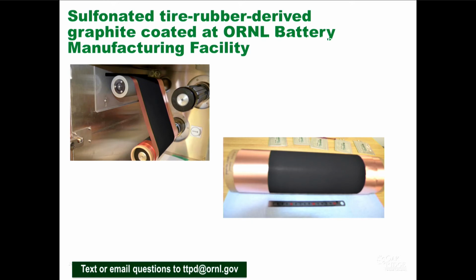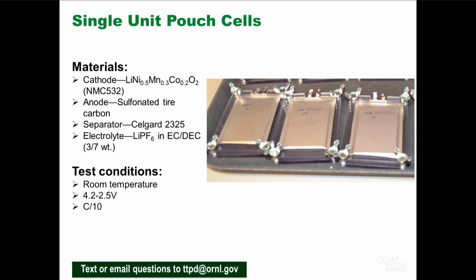So they have taken some of this sulfonated tire rubber derived graphite, and they have made coatings on large areas. You can see copper as the metal contact for anodes. So these are graphite coated copper substrates. And they have also made single unit pouch cells.